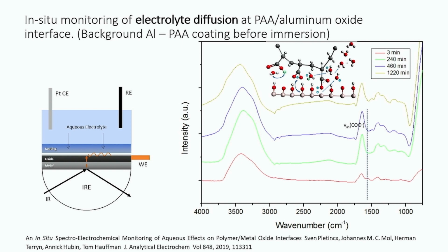You can modify the oxide, you can do some treatments, you can place a very thin coating. In this case it is a very thin polymer film that we applied, and then in situ we can actually measure, for example, how the bonding is formed as a function of time, and how the bonding is destroyed as a function of time, because all the time we can measure in situ in the presence of an electrolyte.